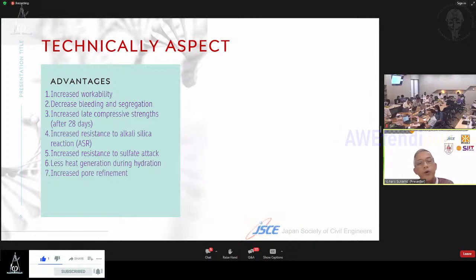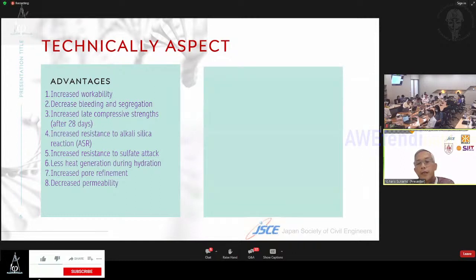Seven, improved pore refinement. And eight, decreased permeability. Fly ash particle size fills voids, resulting in increased concrete density. So with fly ash usage, we can increase the density and get concrete with higher density. But in practice, sometimes we meet problems or disadvantages.